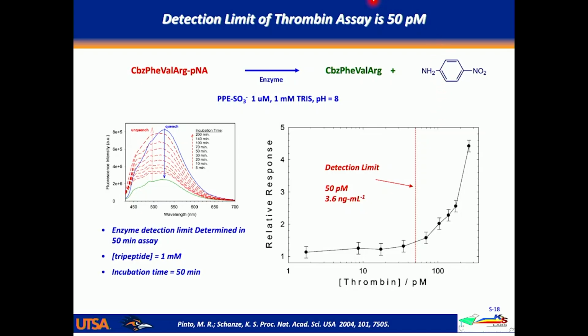And when you add this tripeptide with the para-nitroaniline on it to the polyelectrolyte, you turn off the fluorescence. In this case, we bring it down about 75%. And in this case, we've added, this should be micromolar, not millimolar, so it's 1 micromolar of the tripeptide. And then we add the enzyme, and the enzyme that we used was thrombin in this experiment. And over a period of about 1 hour, you can see the fluorescent signal recovers, and that's due to this slow hydrolytic reaction that's causing the para-nitroanilide to be released from the tripeptide.